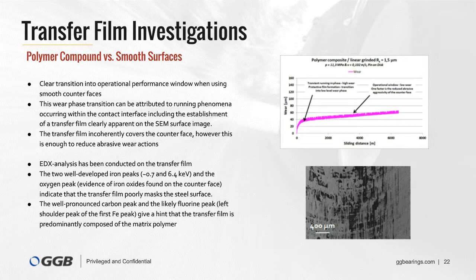The results showed that smooth counter surfaces led to low polymer wear. One of the hypotheses we had is that low to medium rough surfaces promote the establishment of a protective transfer film. Such a film reduces the wear actions, which then lead to low wear.